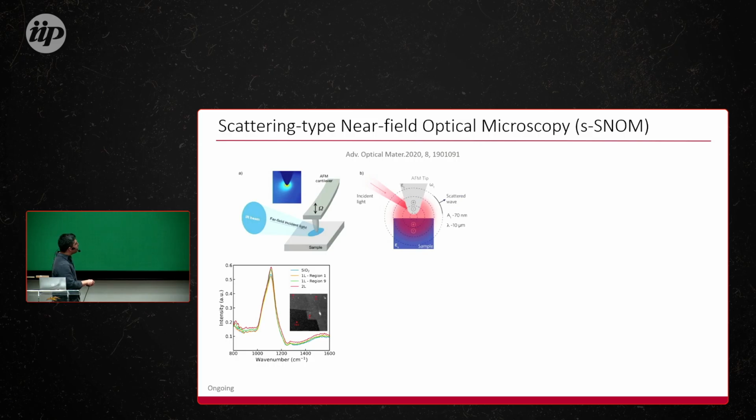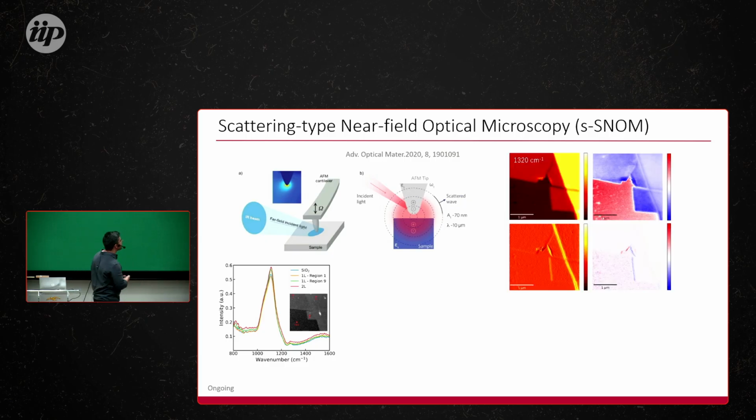So what we notice are two things. One, the intensity is changing. So the intensity variation means that we are doping the material. Another thing that we have, there seems to be a feature over here, about 800, 850, something like that. And there is another feature showing up around here. And we are not quite so sure what that is, but it could be a plasmonic effect that we are actually having in the system. So this is the mapping.